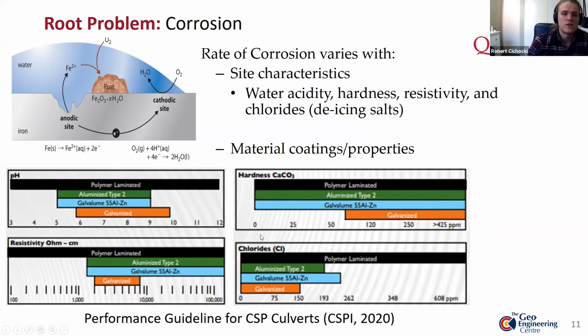Often chlorides are present in the water or the electrolyte through de-icing salts or from the presence of seawater. Essentially, chlorides contribute soluble ions to the electrolyte, so water is able to conduct electricity more freely, which decreases its resistivity and increases the rate of corrosion. So the Corrugated Steel Pipe Institute keeps up to date with how to monitor these site characteristics and outlines how to pick materials that should be adequate for the design service life based off of them.